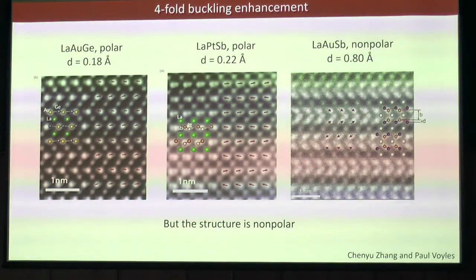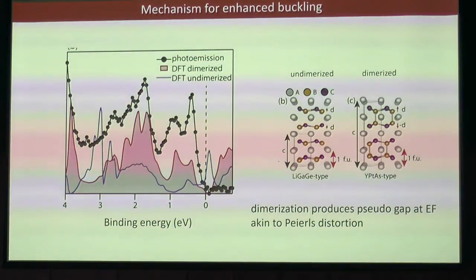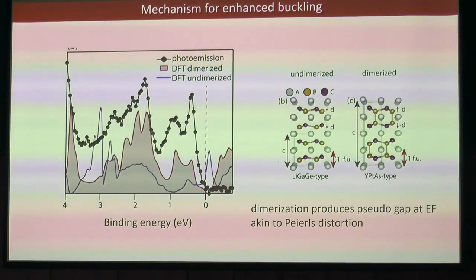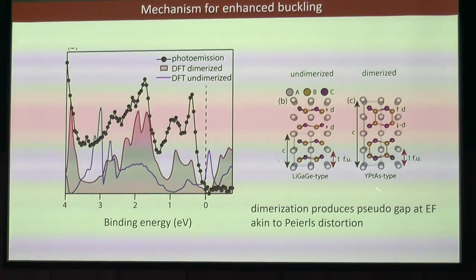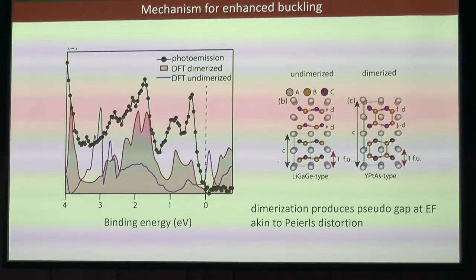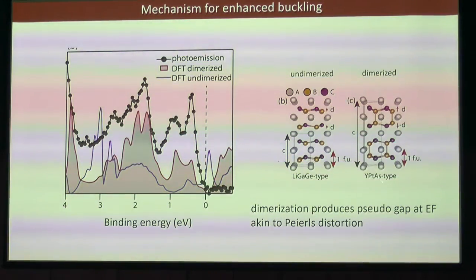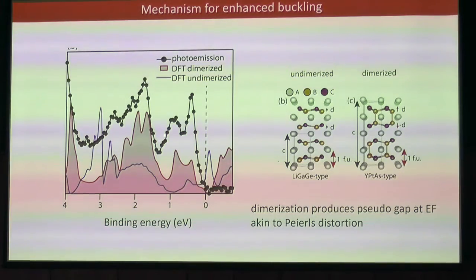And to prove to you that we think this is really an electronic or Peierls-like distortion, we did some photoemission spectroscopy measurements. These are just angle-integrated measurements. We'll first look at the DFT calculations. If you take this lithium gallium germanium type structure and artificially impose the unbuckled structure, what you would find is this blue curve with a very sharp peak in the density of states right at the Fermi energy. If you allow it to relax into this structure at the level of DFT, what you would find is this shaded red density of states with a suppressed density of states at the Fermi energy, suggesting that it is some sort of electronic-driven reconstruction. And if we measure in photoemission, we get pretty good qualitative agreement with the density of states calculation.